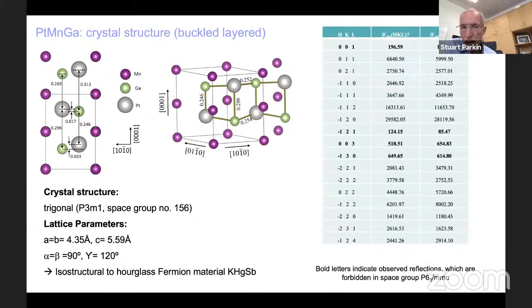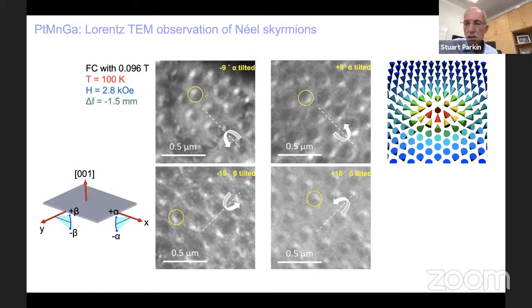And this, again, through Dzyaloshinskii-Moriya exchange, can stabilize a very unusual Néel skyrmion-like structure that we can observe by tilting a lamella in the transmission electron microscope. And we can see these are clearly Néel skyrmions. And it's the first observation of a Néel skyrmion in a metallic system.